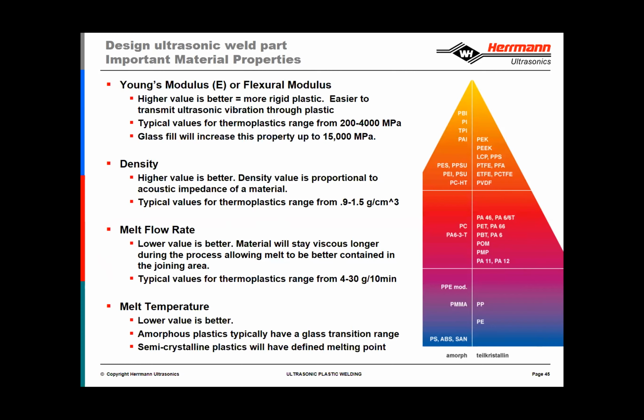So if you have two similar materials that, number one, first have to be chemically compatible, but when we talk about ABS and acrylic being bonded together, we also have to look at the melt flow rate and melt temperature. The melt flow rate should be within 10% of one another, and the melt temperature should be within 50 degrees of one another. This can change depending on the grade of material that's used. So if you have an ABS, for example, that's extrusion grade, and an ABS that is injection molding grade, they may have very similar melt temperatures, but they may have properties that change their melt flow rate. So even though they may both have a base resin of ABS, again, the melt flow rate and the processing temperature need to be in a similar range to get that true homogeneous bond that we're looking for.